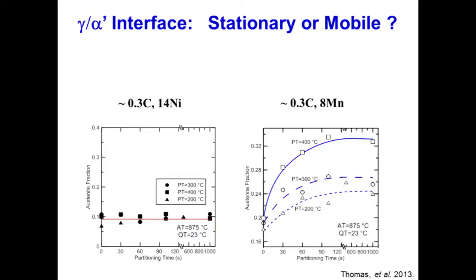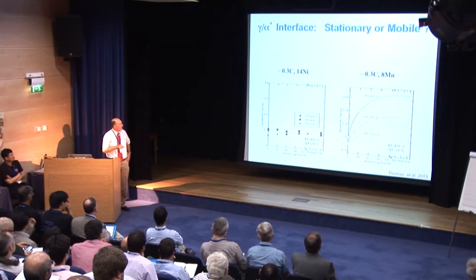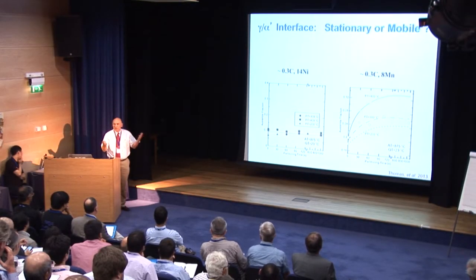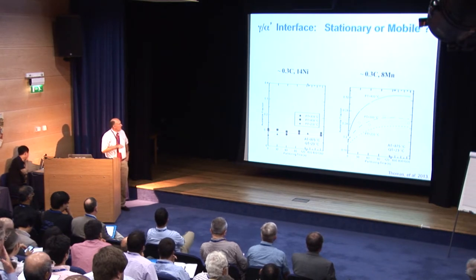The last comment I want to make: we've had a lot of discussion about whether the martensite-austenite interface is stationary or mobile. There's been some interesting modeling work done at Delft in particular. One of my former students, Grant Thomas, looked at some higher alloyed steels, not intended for commercial applications, but intended to study the partitioning mechanisms. One of the things we looked at is the change in the austenite fraction during partitioning in these steels, where you could quench to room temperature and then partition subsequently.